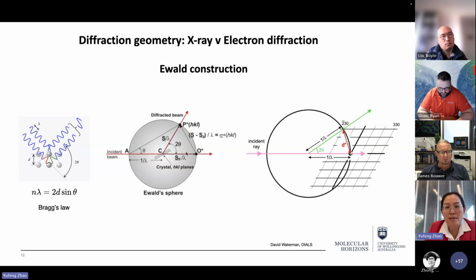So here's the incident beam and the diffracted beam. This angle is 2 theta, which is a thing to consider. In order for the diffraction reciprocal points to be captured on this sphere, it has to satisfy Bragg's law. We call this sphere the Ewald sphere, with a radius of 1 over lambda. In the experiment, we rotate the crystal, trying to get as many reciprocal points on the sphere surface as possible, so we can get a good structure.